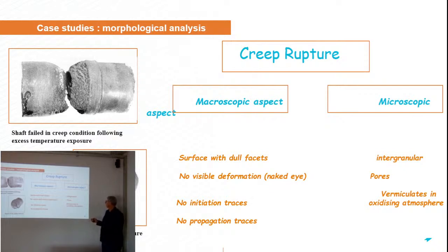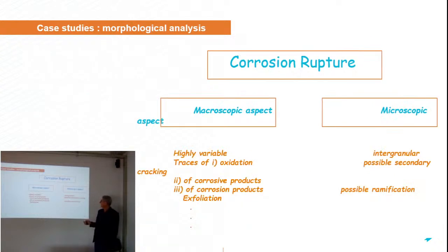And when you go to the microscopic scale, you can see that the fracture is intergranular, you can see pores, and you can see also vermiculates in oxidizing atmosphere as well. Corrosion fracture, highly variable here. You can see traces of oxidation, of corrosion products, and in some cases, for example in aluminum alloys, you can see some exfoliation as well. The microscopic aspect reveals that the fracture is intergranular, with possible secondary cracking and possible ramification due to the intergranular corrosion in planes making an angle with the main fracture surface.